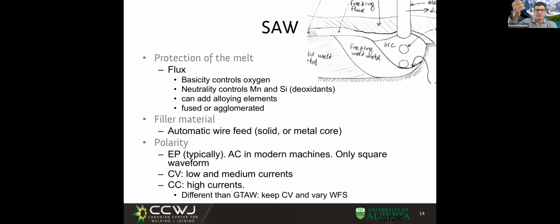If, for example, the wire starts to come too close to the plate, typically in MIG, I would increase the current. But in this case, I cannot increase the current. In subarc weld, I cannot increase the current because it's constant. But if the wire starts to get too close to the plate, I detect that the voltage is too low, and what I do is slow down the wire feed speed. But this has nothing to do with resistances. This has everything to do with a balance of mass and energy, which we will see in detail later in the class.